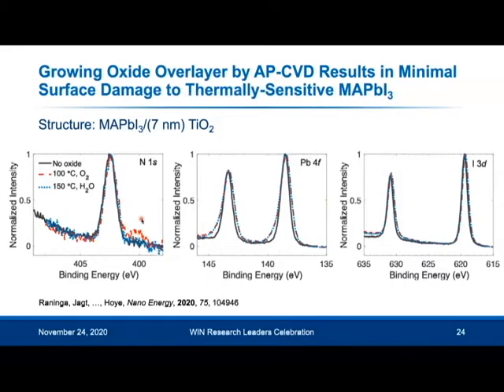So there is some degradation of the methylammonium. And you can see that the lead peak and the iodine peak becomes slightly wider. So there's degradation of the organic component and the inorganic sublattice. At the same time, the amount of degradation is very small. It's much less than what you would get if you were to use alternative techniques at the same temperatures where even the bulk would degrade. So this is quite promising.